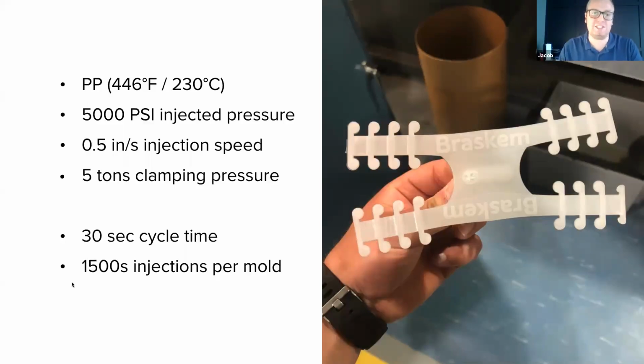And we knew we'd be watching the mold operate on a more continuous basis. With these strategies in this geometry, we were able to achieve 1,500 shots per mold, and we could have kept pushing those molds even further. That was with the high temperature resin. I'm very optimistic that if we were to use the new rigid 10K resin, we could push those numbers even further. So that's the next step.